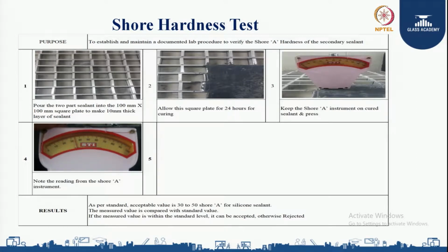As per the standard, the acceptable value is 30 to 50 shore A for silicone sealant. The measured value is compared with the standard value. If the measured value is within the standard level, it can be accepted; otherwise, the sealant requires more curing.